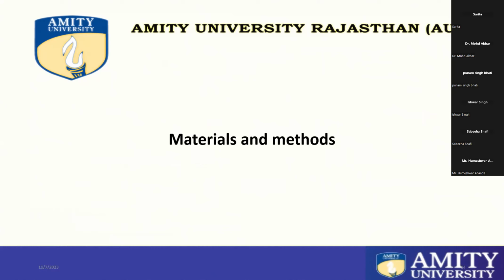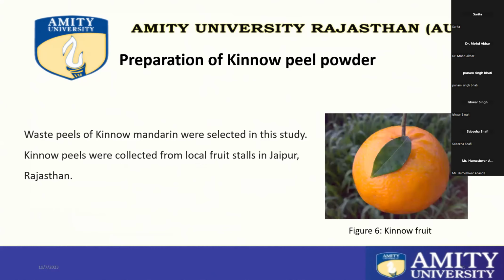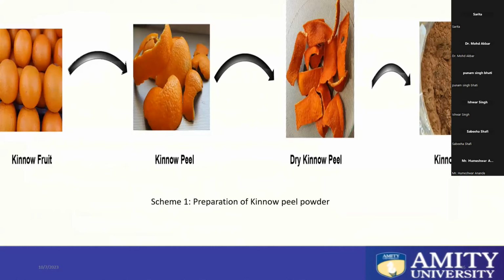So the materials and methods used for my work were waste peels of Kinnow mandarin fruit, which were selected. These were collected from the local fruit stalls in the city. You take the fruit, you peel it off. The peels were dried in the oven at 70 degrees Celsius for 24 hours. And once it was dried enough, they were ground to Kinnow peel powder.